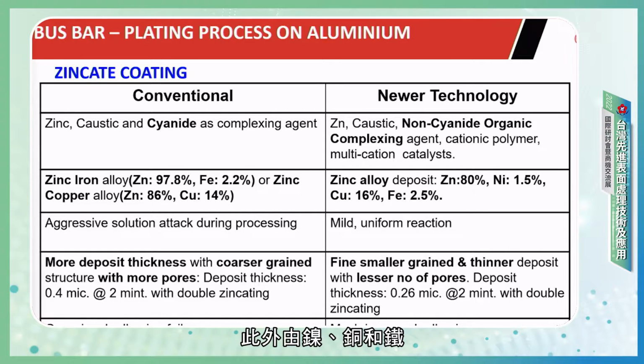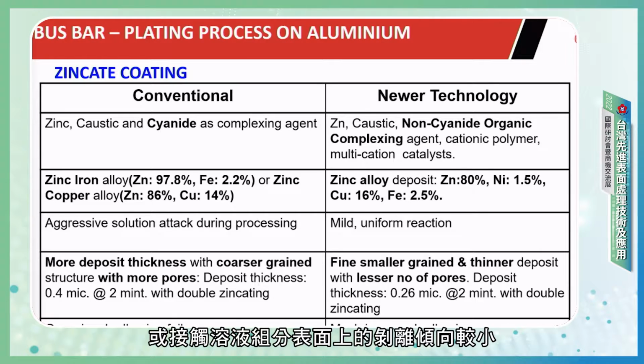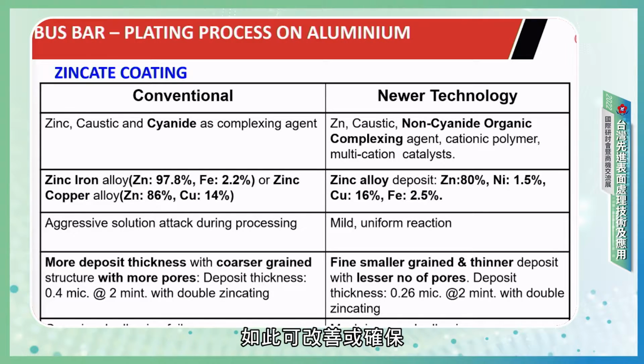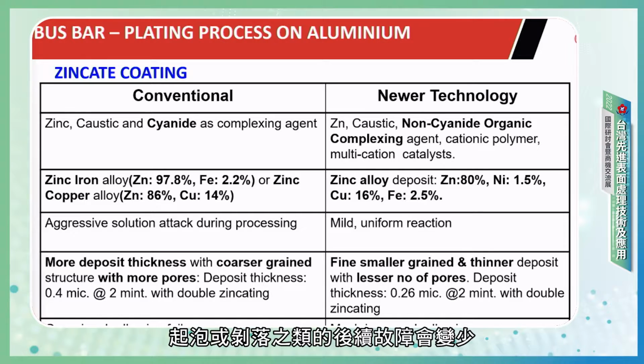Furthermore, being a true zinc alloy, consisting of nickel, copper, iron, as compared to the traditional processes, binary alloy, zinc and iron or zinc and copper, this is fairly less corrodable. For example, if we go from the zincate to subsequent coating processes, this deposit has less tendency to strip off at the contact surface or component touch surface. So it improves or ensures the subsequent deposit adhesion. With the newer technology, we can get better adhesion, so subsequent failures like blisters or peeling off gets reduced.